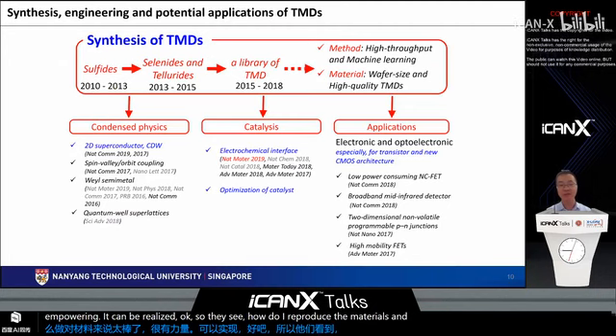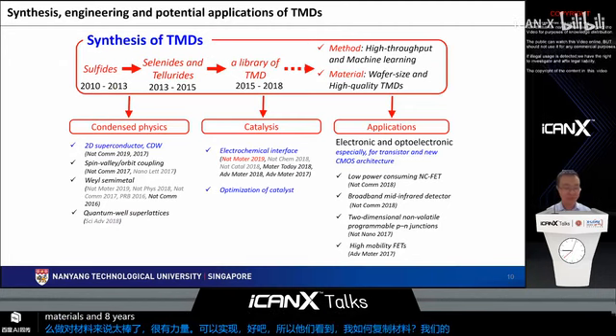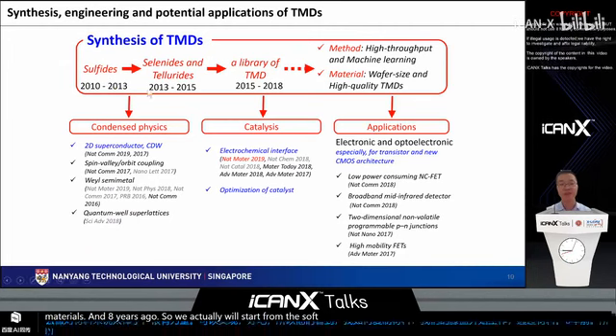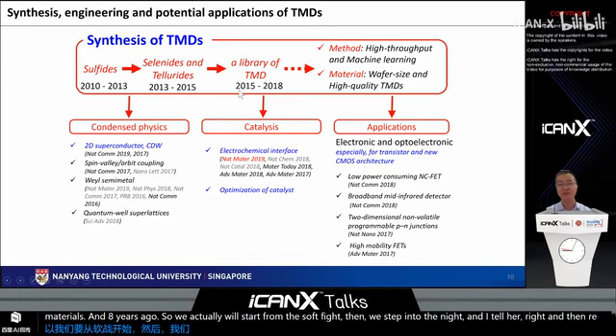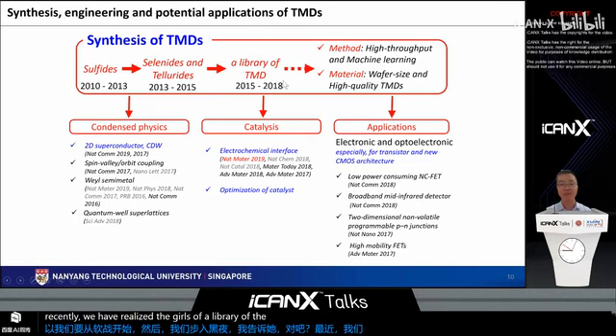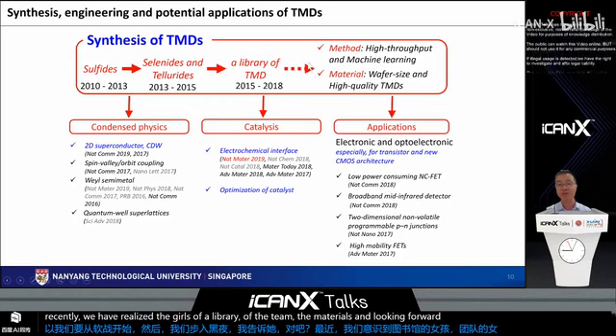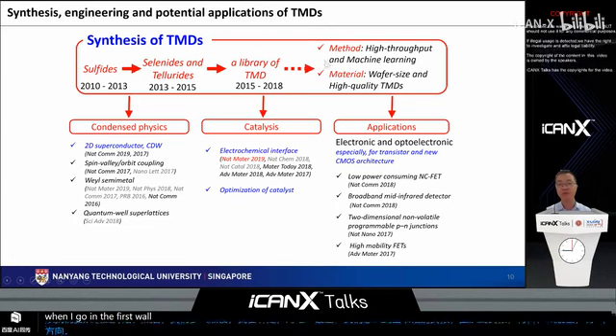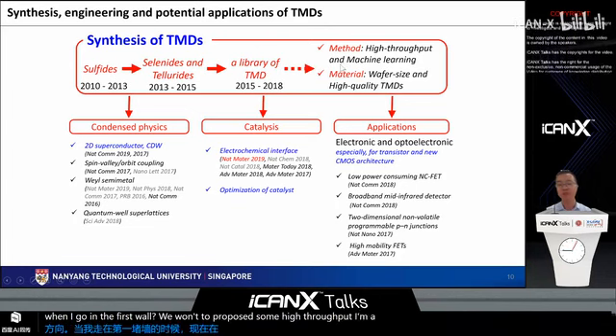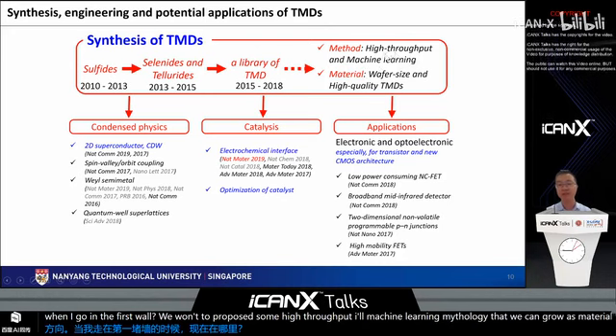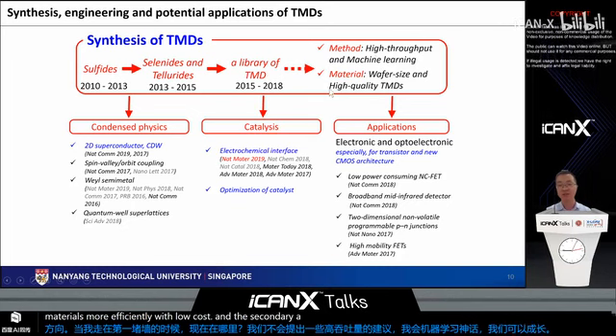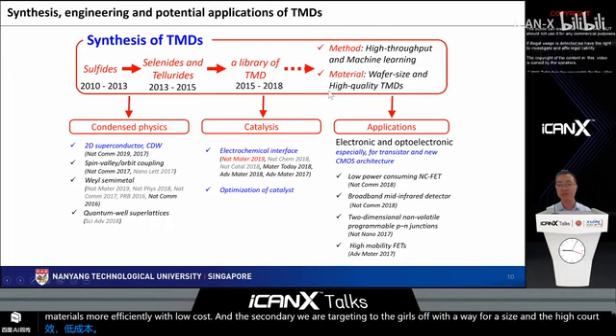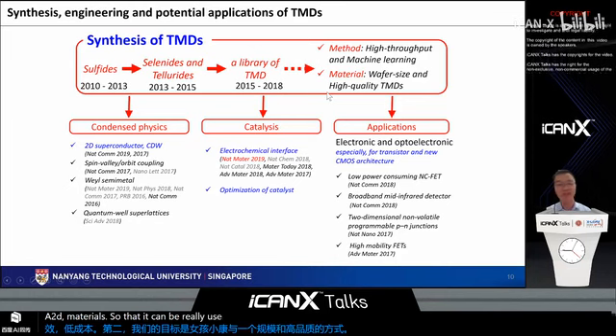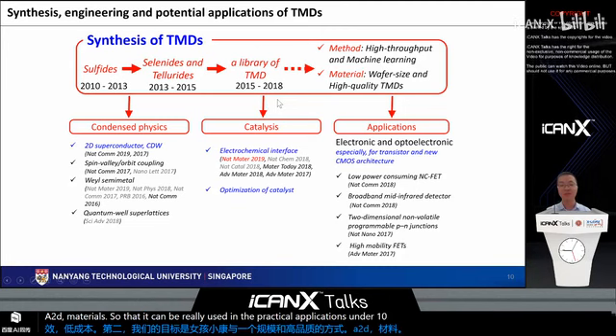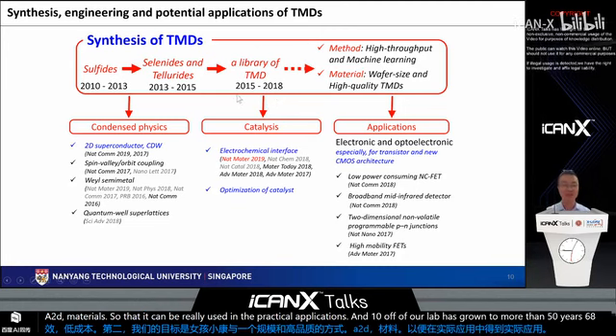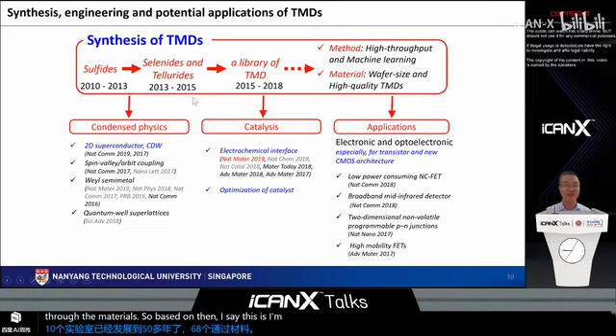And our lab started working on 2D materials 8 years ago. We started from the sulfides, then we stepped into the selenides and the tellurides. And then recently, we have realized the growth of a library of TMD materials. Looking forward, there are 2 directions we're now going. First of all, we want to propose some high throughput or machine learning methodology so that we can grow the materials more efficiently and at low cost. And secondly, we are targeting the growth of wafer-size and high quality 2D materials so that they can really be used in practical applications. Till now, our lab has grown more than 50 or 60 2D materials. Based on them, I think this is a valuable library for us.